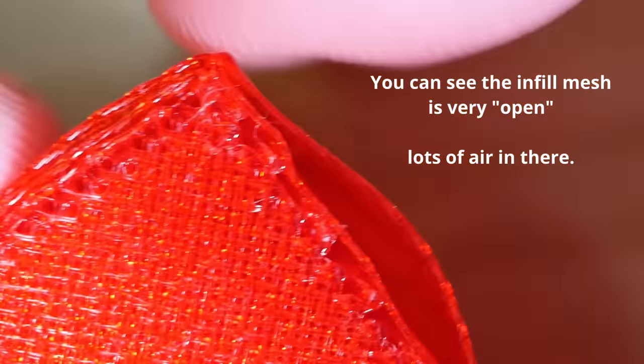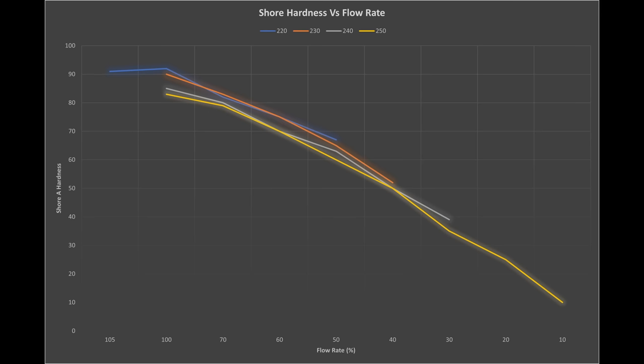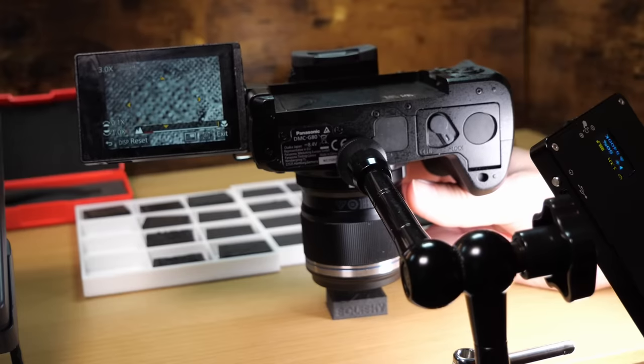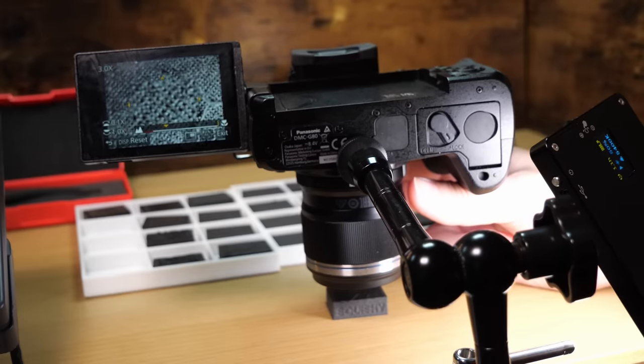So I think we can probably assert with some level of confidence that when we look at this graph for the foaming TPU, you probably have a foaming section where the foaming TPU is performing adequately and filling the gaps efficiently, and then a section where the integrity is still maintained, or at least it looks like it's still maintained, but the additional gaps that you are creating by under extruding, they're essentially being filled with air and you just can't see that. I can't prove it, but I can take some macro shots, which kind of does prove it.